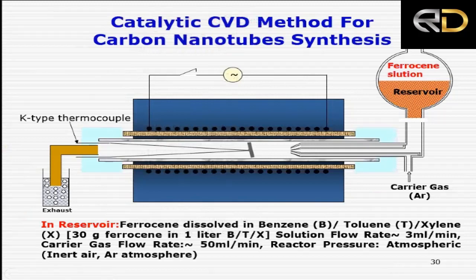Now, there are a number of methods to prepare these nanotubes, but a very simple method which we have adopted in our laboratory for demonstrating to the students is this: we dissolve ferrocene in an organic solvent like toluene, benzene, xylene, etc. And then we slowly pass this spray into the furnace where a platinum foil is kept at about 800 degrees centigrade. The ferrocene is decomposed and gives you nanodimension iron. This nanodimension iron converts the organic compound like benzene, xylene, toluene, etc. to nanocarbon. And this nanocarbon is mostly in the form of multi-walled carbon nanotubes.